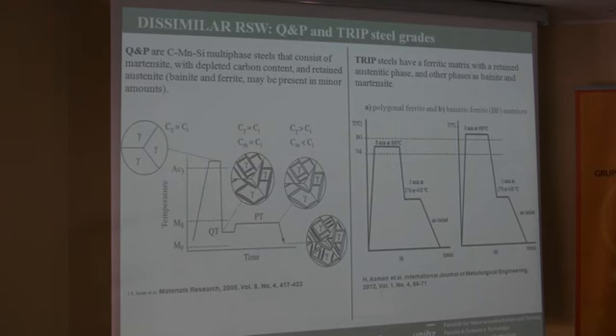In particular, here you can see a comparison between steelwork heat treatments that are generally used for the fabrication of these steels. In particular, on the left side, you can see fabrication processes for the quenching and partitioning steels. As you can see, initial austenitic heat treatment, rapid quenching at a temperature between martensitic start and martensitic finish, and maintaining at this temperature for a certain given time in order to allow the carbon present in the martensite to go inside the austenite, to promote this movement of carbon atoms. We need to increase a little bit the temperature of the steels, and then we have a final quenching in order to obtain a final microstructure that generally consists of retained austenite and martensite. However, in some cases we can also have some amount of bainite and ferrite in these peculiar steels.